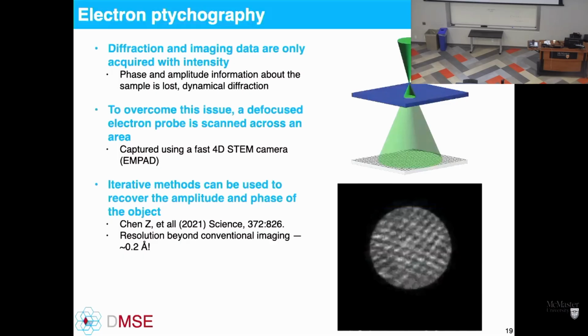Previously, again, we were losing a lot of information because all that we could acquire from diffraction and imaging was intensity. Anytime you do electron microscopy it's fundamentally quantum mechanics, and as soon as you measure something, it's the intensity. You've lost all phase information about the electron when it reaches the detector. So in addition to that, electrons are pesky in that they scatter dynamically within the sample. They really like to scatter strongly off the nuclear cores of the material, and as a result, this makes interpretation very difficult. You cannot use kinematical approximations in these materials like you can with X-rays.